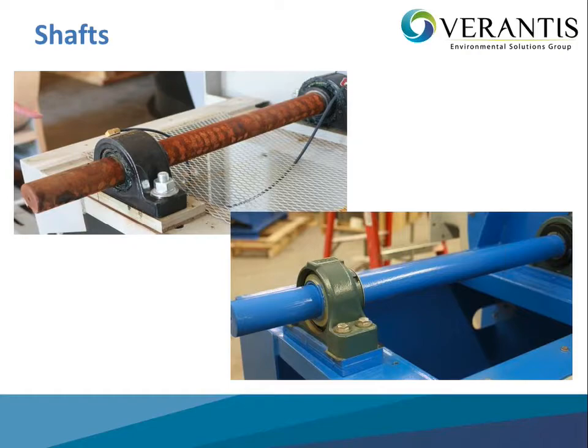Unpainted shafts will start to corrode in as little as 24 hours. On the right is our standard carbon steel shaft, which we paint after assembly, which will greatly extend the service life with reduced corrosion.